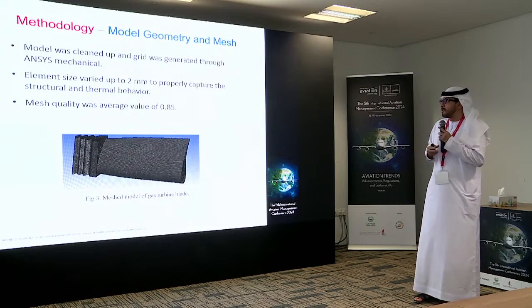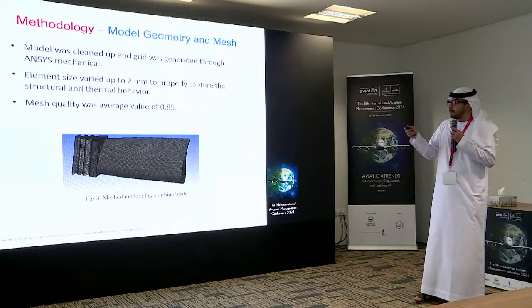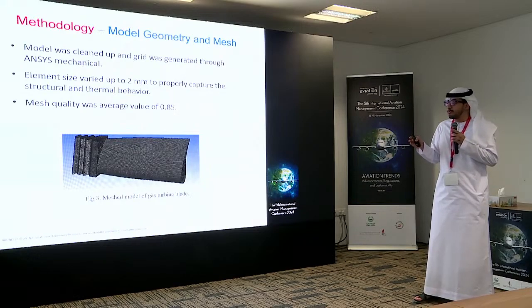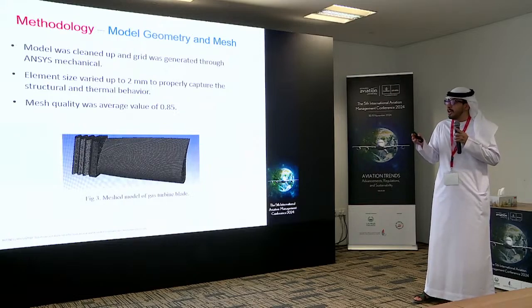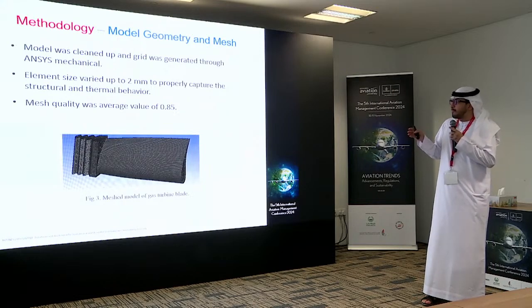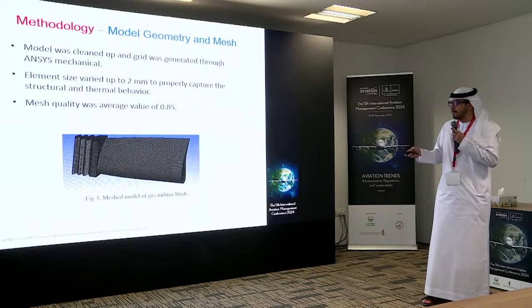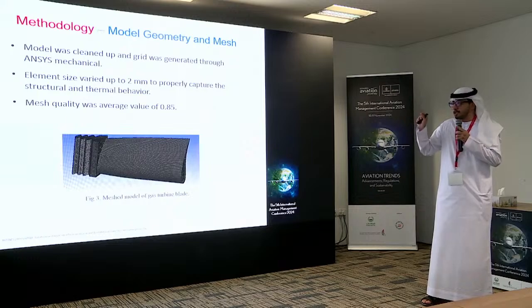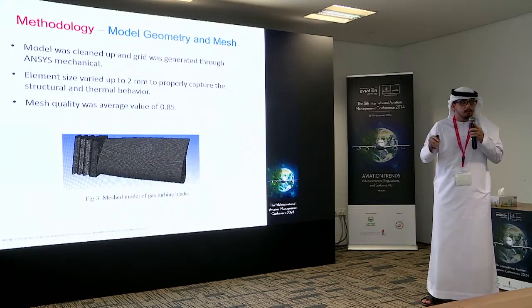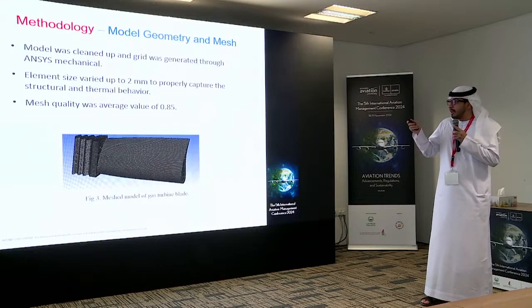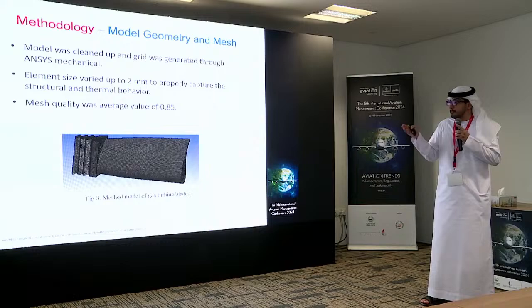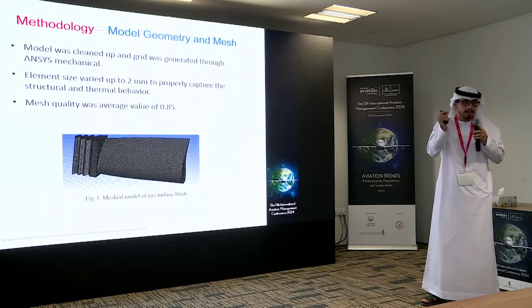We'll move now to the methodology. In the methodology, we use a software called ANSYS. It's a software used for simulation for mechanical and thermal analysis. A model was cleaned up and a grid was generated through ANSYS Mechanical. Element size varied up to 2 millimeters to properly capture the structure and thermal behavior. As you can see in figure 3, the smaller the elements get, the better result we will have. These small elements help us capture accurate results for the simulation. Of course, you are limited by the computational power that you have.